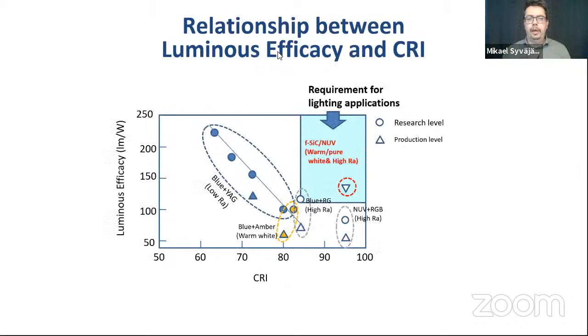In comparison to the LEDs of today, you can have very efficient LEDs. On the left side of this graph, you see the efficiency using the blue LED plus phosphor, but then the blue tone is penetrating. If you want a better light quality, you need to do compromises, and then the efficiency goes down. On the bottom, you see the CRI, which is basically how white is the light. If you start to make compromises, you lose efficiency. In this blue box on the top right, you see the silicon carbide based LED, which has a very high light quality and also fairly high efficiency. That is the uniqueness of this method.